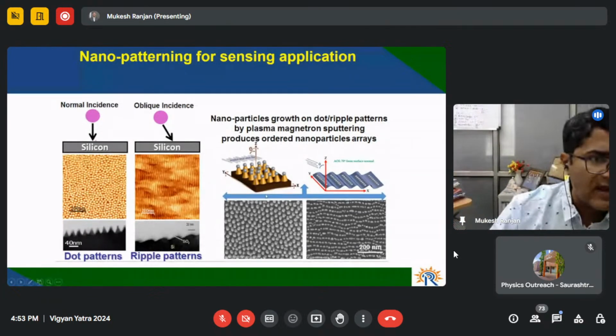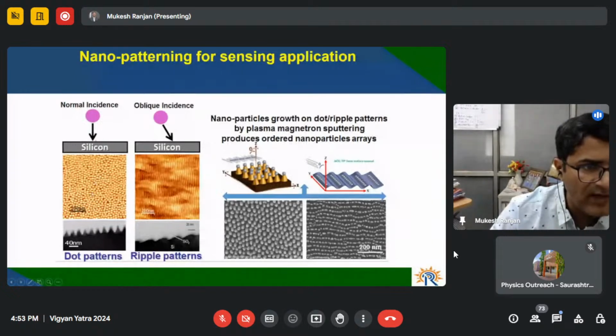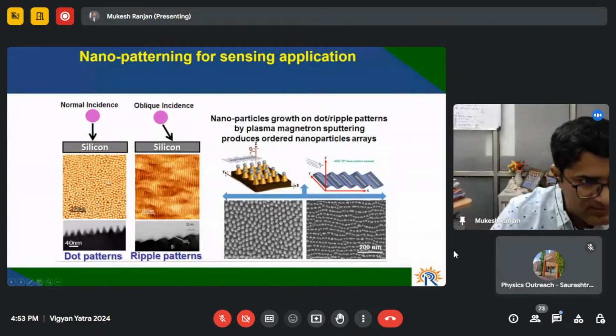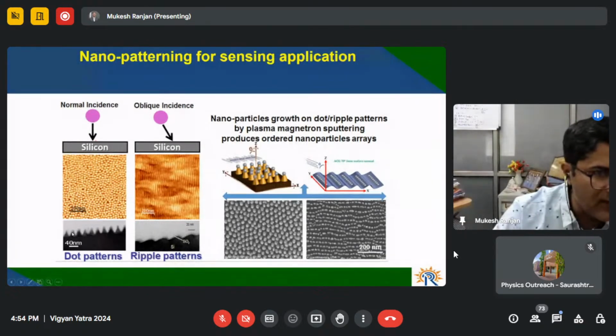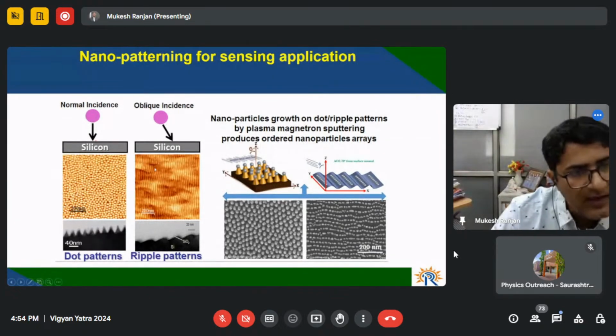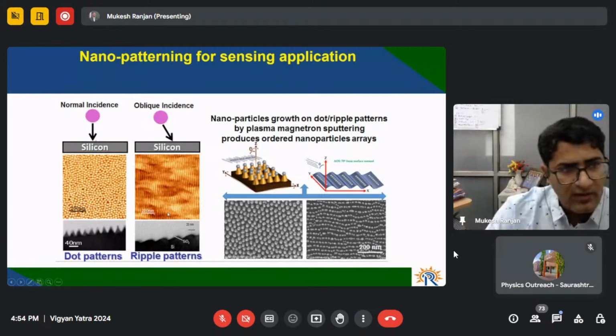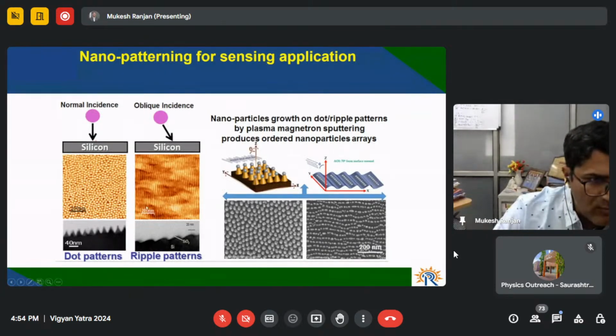So when the ions are hitting the surface, they can make very regular structures on the surface. In the first example, what you see in the atomic force microscopy image, it can make freestanding nanodot structures. And if the ions are falling at some angle, it can make a wavy structure, this kind of pattern. If you see, the scale bar is around 200 nanometers, so you have control of making a regular nanostructure on the surface simply by changing your plasma parameters.